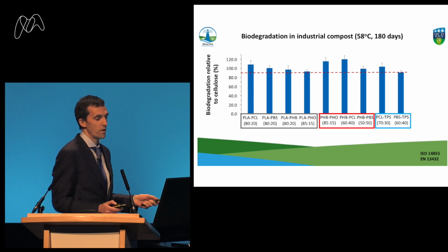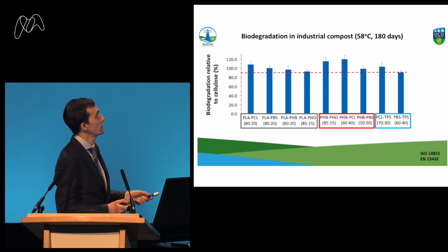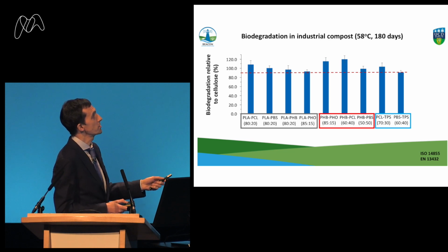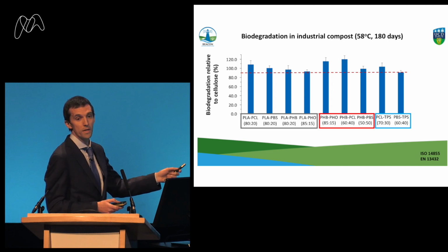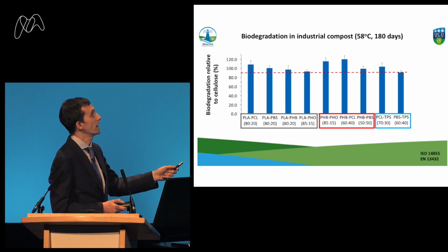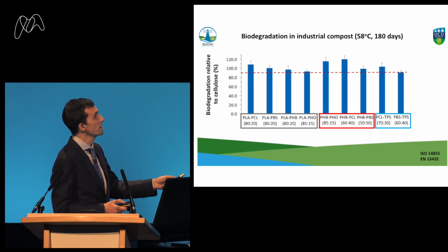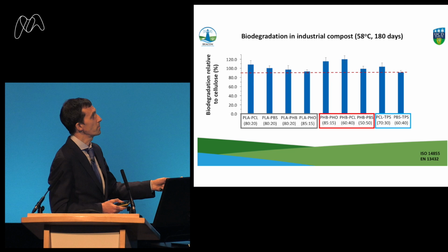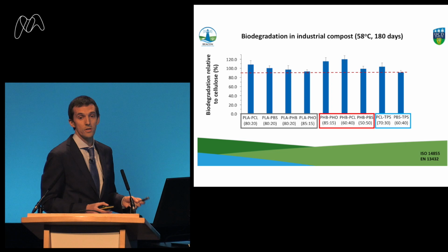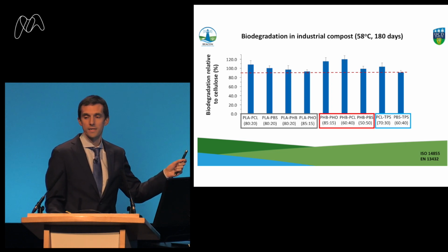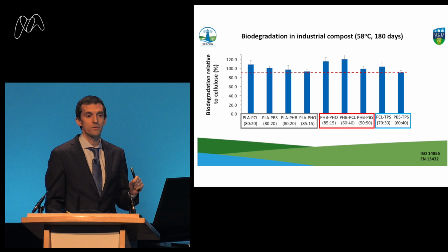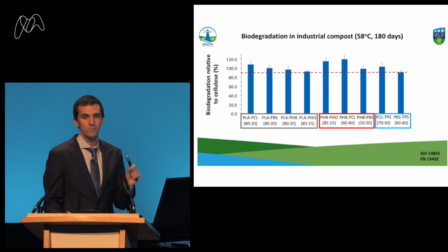What I want to highlight is that in industrial composting, when we took PLA polymers and blended them with PCL, PBS, PHB, and PHO, they all make the standard. They all meet the compostability standard in an industrial compost. Similarly, PHB blends with PHO, PCL, etc., make the standard, and also TPS. They also make the standards. So for industrial composting, we have a lot more plastic blends that we tried, but it always makes the standard. So industrial composting can address plastic waste because it can help to manage these plastics and have full biodegradation.